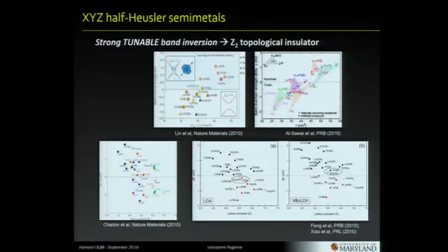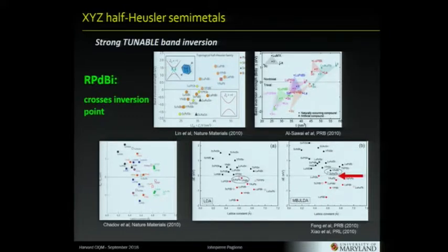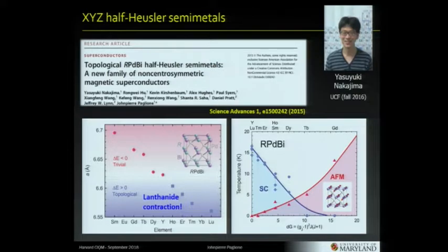We initially wanted to focus on something near the crossing point and try to chemically tune through there, to see if we can explore the transition between trivial and non-trivial topology. So we started in this area here, which is the palladium-bismuth compounds. This was some work about 3 years ago that got published. Just looking at the rare earth palladium-bismuth series, you can tune, just by changing the rare earth position, across this crossing point, theoretically.